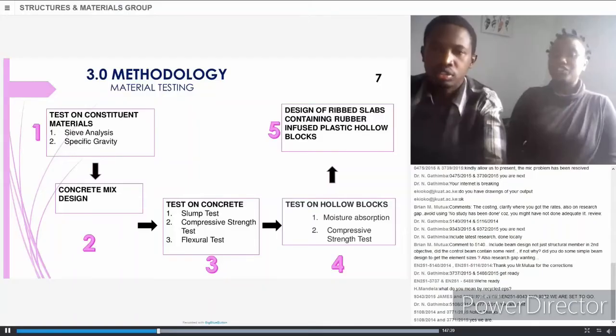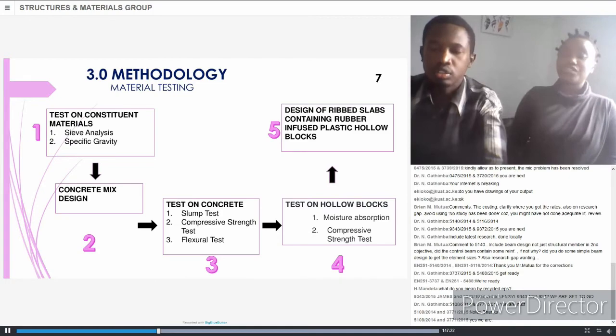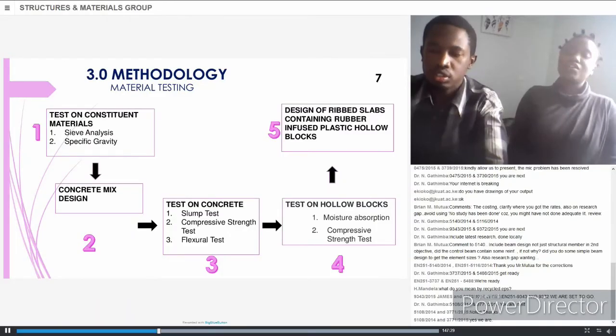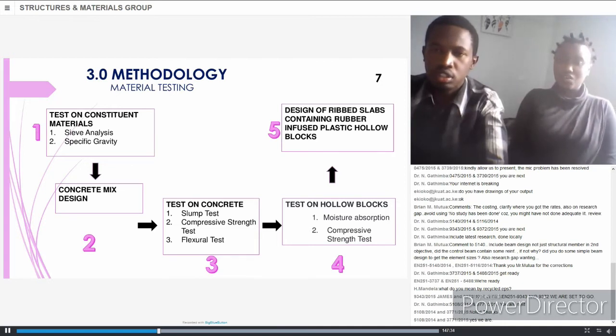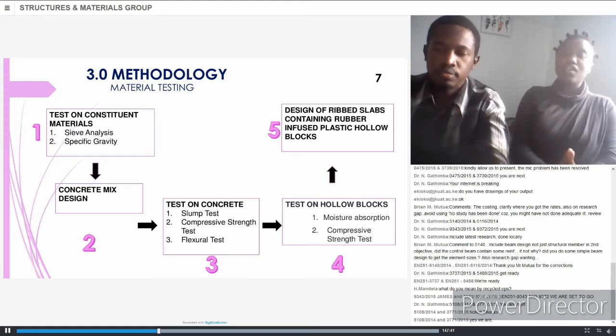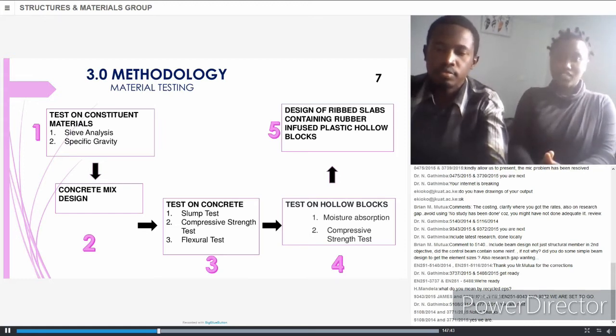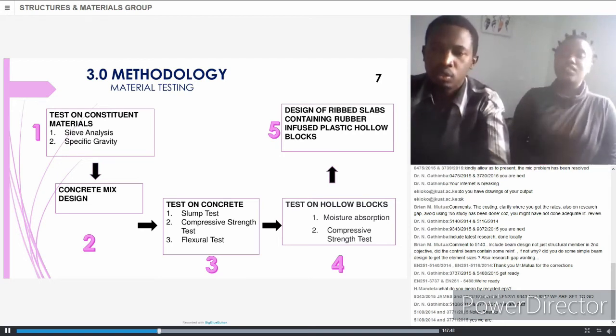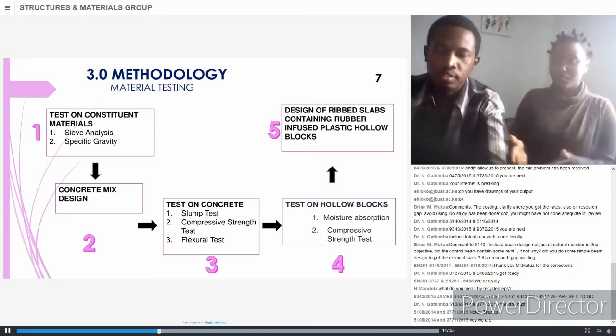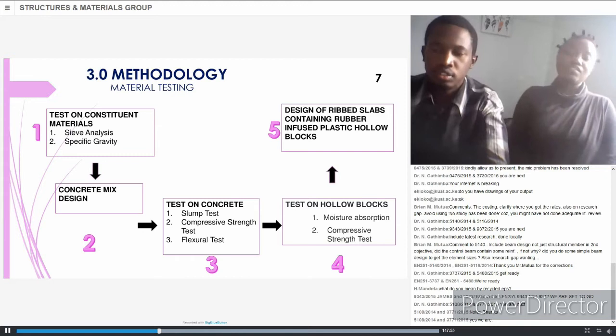In our methodology, we tested the specific constituent materials, that is plastic and rubber, conducting analysis using specific gravity. Afterwards, we designed a concrete mix with varying proportions of the aggregates, for example, 70% rubber and 30% plastic, 60% rubber and 40% plastic, then a 50-50 mix, and the reverse, like 30% rubber and 70% plastic. And then we had tests on concrete.